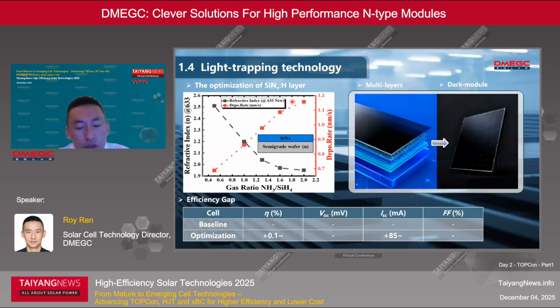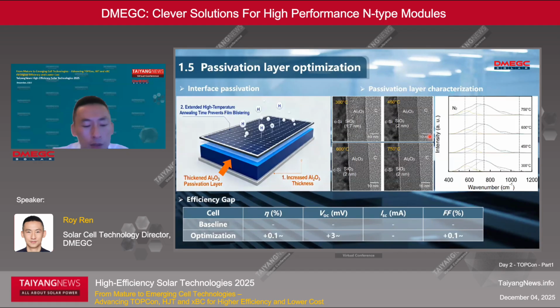For light trapping technology, we optimize the silicon nitride layer and the multi-layers. There may be low refractive index film layers, such as silicon oxide or silicon oxynitride. With this technology, we will obtain all black photovoltaic modules. For passivation layer optimization, we focus on optimizing the thickness of the interfacial alumina and the annealing temperature to achieve a better interfacial passivation effect. We know that alumina can provide better interfacial passivation and further passivation effect. So we can achieve an efficiency improvement of over 0.1%, mainly in VOC and fill factor.